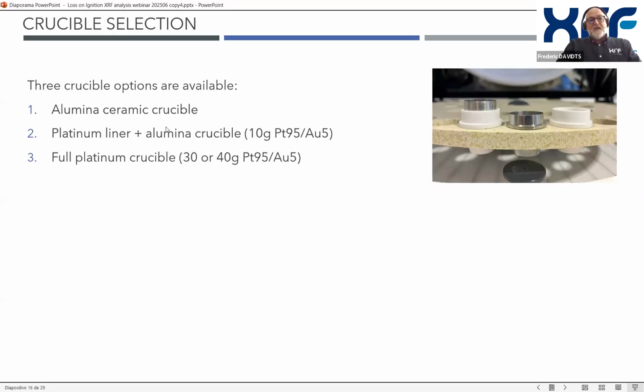Now, what crucibles to use with the machine? We have three options available. We can work with the classical alumina ceramic crucible, or with platinum liners that are introduced in the crucible, so 10 grams of platinum gold alloy, or we can work with a full platinum crucible.